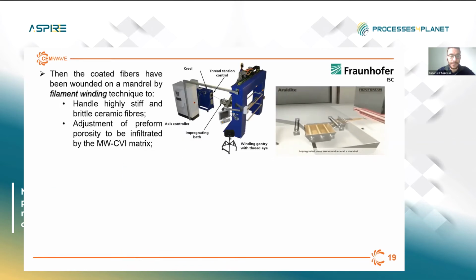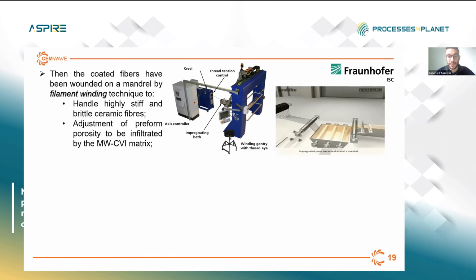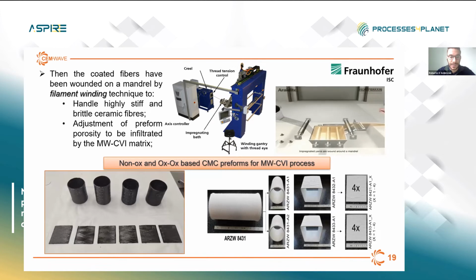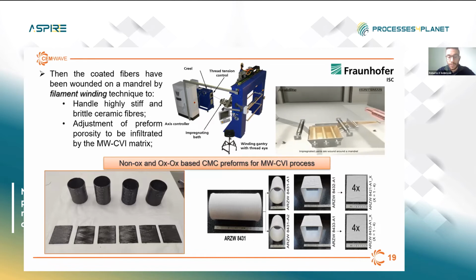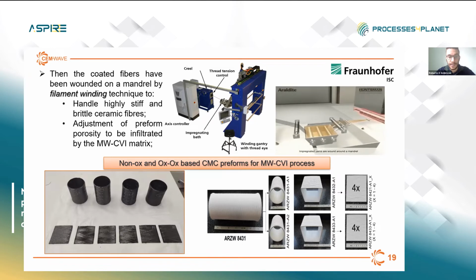Following, the next step regarded the coated fibers, which have been impregnated, passing them through a bath with a ceramic slurry, and winding them on a specific core depending on the final geometry, which has been done by filament winding technique. Why this technique? Because at first it allows a very fine adjustment of the fiber reinforcing architecture, and secondly, because it is not easy to handle stiff ceramic fiber rovings as our coated ceramic fibers. So once optimized the textile processing parameters, the preforms have been thoroughly dried and thermally treated to remove them from the cores, obtaining the final geometries here displayed, which had tubular and plate-shaped geometries for both categories of materials.